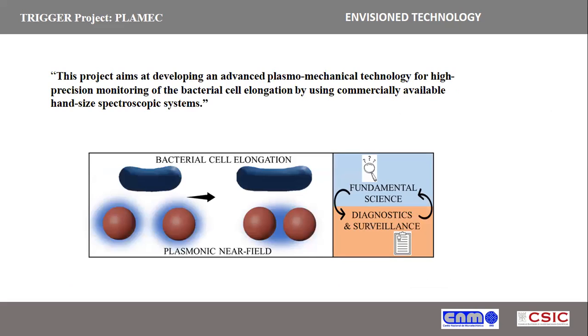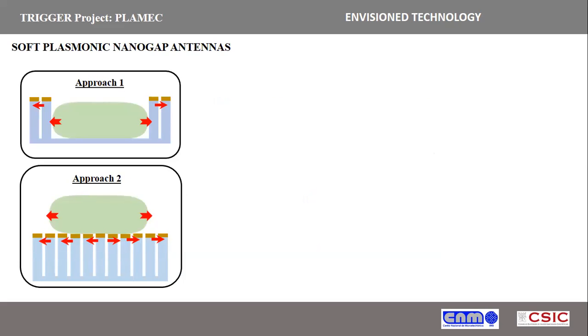So in summary, the objective of this TRIGGER project is the development of plasmomechanical technology for high precision monitoring of the bacterial cell elongation using a simple spectroscopy measurement. So we propose the use of gold-coated soft plasmonic nanogap antennas to measure the bacterial elongation. To this aim, we foresee two different approaches. Approach one consists of confining the bacteria between dimers of antennas. And approach two involves attaching the bacteria on top of an array of plasmonic antennas.